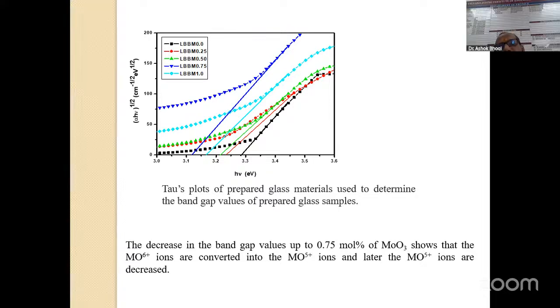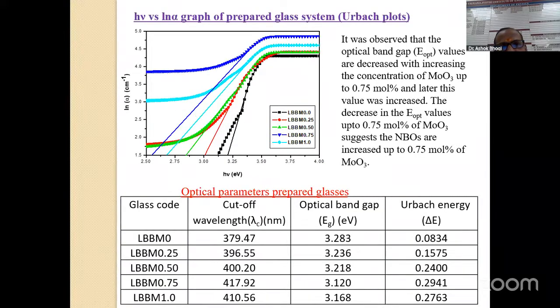So this is the Tauc plot of the prepared glass samples. From these Tauc plots, we have measured the indirect band gap energies. The indirect band gap energy values decrease with increase in the concentration of molybdenum up to 0.75 mole percent, and later the value was found to increase. And next one, these are the Urbach energy graphs. Here the Urbach energies are observed to increase with increasing concentration of molybdenum up to 0.75 mole percentage, and later the value is found to decrease.